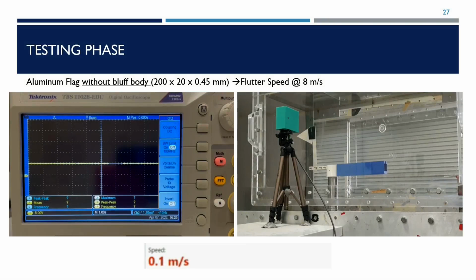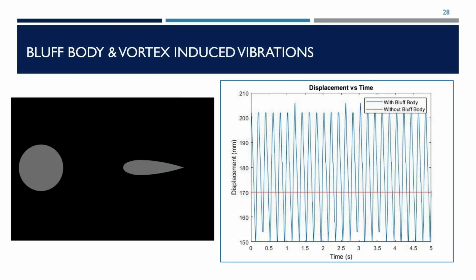From the 3 tests conducted, we can conclude that the aluminum flag with the dimensions 200 by 20 by 0.45 millimeters will give us the best chance at achieving the lowest critical flutter speed possible. This critical flutter velocity will be further reduced when we attach a bluff body to the flag. Now that we have chosen our flag, I will explain the effect of attaching the bluff body to it.